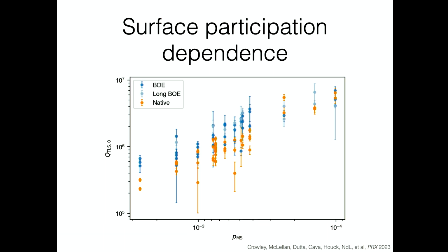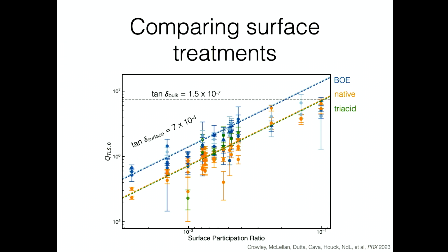And then I can do things a little bit more sophisticated, which is to start to do different kinds of surface conditions. So I can dip it in acid, try to oxidize the surface, and do lots of surface conditions. And what I find is that all of this data fits best to having some surface-related two-level system loss, but also a bulk-related two-level system loss that has to come from the underlying sapphire.